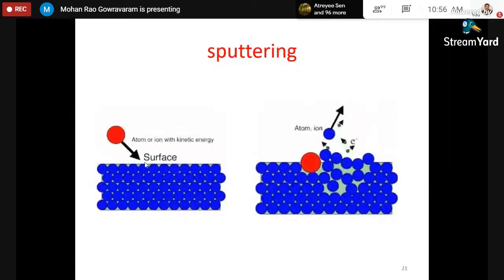Sometimes the striker may not even reach the lattice. Exactly similarly here, depending on the ion energy and the angle at which it is bombarding, the atom that is coming out from here will vary. So the ion transfers its energy and momentum to the surface atoms, and these surface atoms come out and travel because it is done in vacuum, and then deposit onto the solid surface that is kept in the line of sight. This is the sputtering process. Now here is basically the energy transfer that is taking place. No heating is taking place. So no vapor pressure concept.